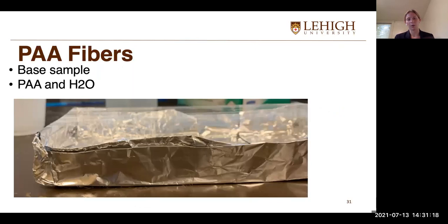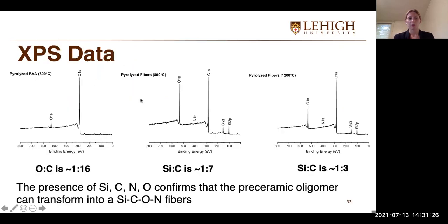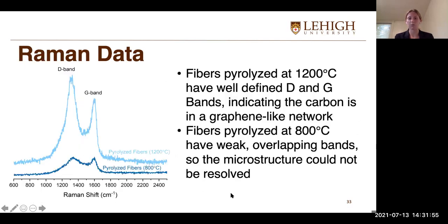I will note at first that I did also create PAA fibers as a base sample, and they're just made of PAA and water. So as you can see here, some XPS data. This is the pyrolyzed PAA, which I pyrolyzed at 800 degrees Celsius. The fibers pyrolyzed at 800 degrees Celsius, and then the other pyrolyzed fibers at 1200. Again, similar to the powder, I wasn't sure if this was actually going to create the ceramic SiCN fibers. So this allowed me to confirm that it was in fact creating those ceramic fibers.